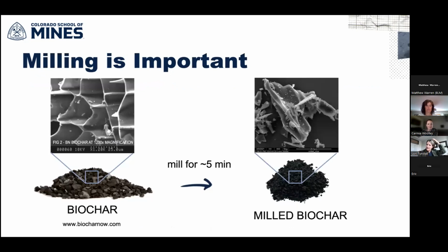So one thing that is certainly important, and this accounts for some of the strength improvements we've seen: you have to mill the char. If anybody has handled biochar before, you'll know that it's very fragile. You can break it up in your hand, and that's because of this large pore structure that you can see on the left side. Before it's milled, biochar looks basically like the biomass. If you've heated wood chips, it's going to look like wood chips, but be really fragile. Once you mill it down to a powdered form, it's pretty strong.